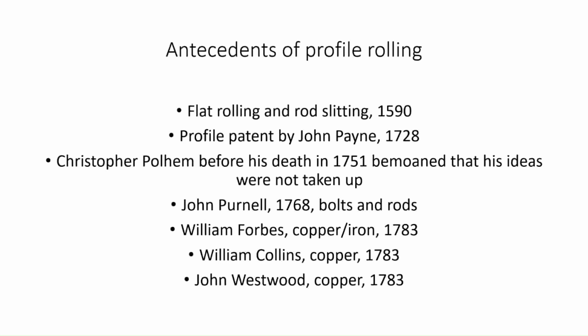But then an Englishman called John Purnell in 1768 started to use profile rolls for making bolts and rods, particularly in copper. And then suddenly that took off in 1783, which was the same date as the patent that Henry Cort had. And basically that was because there was a sudden demand for copper bolts from the Navy. They had decided that they were going to use lots of copper sheathing to protect the hulls of their boats from the various worms that they got out in the tropics. But the trouble was that the copper sheeting reacted with iron bolts. So they had to replace the iron bolts with copper bolts. And so suddenly there was a huge demand for copper bolts. And I think at that point, rolling became economic.